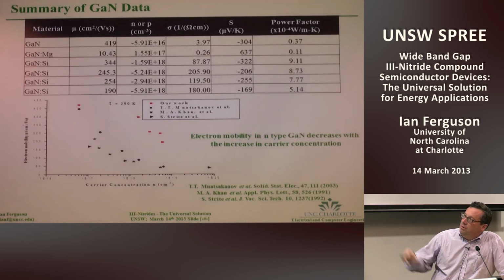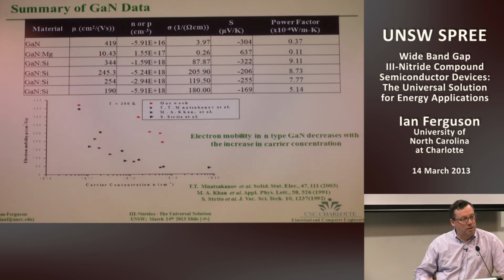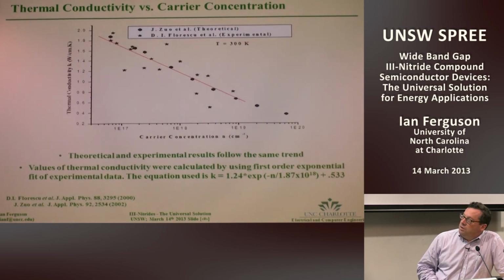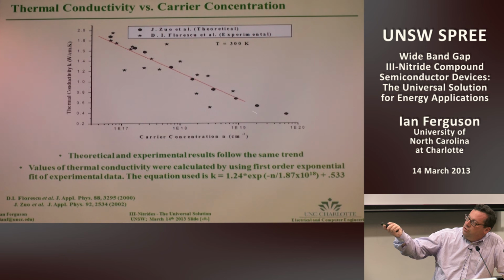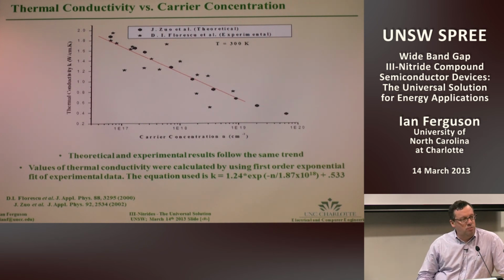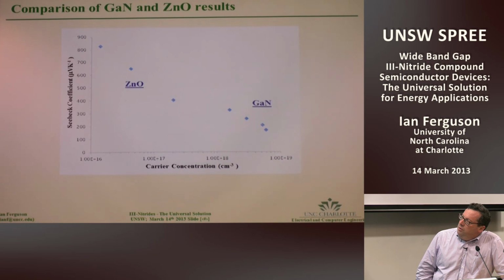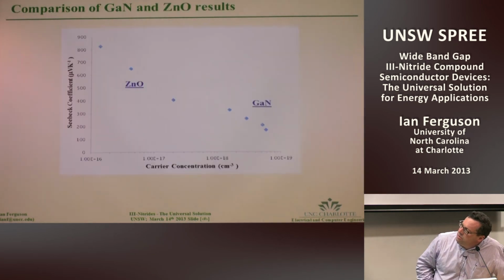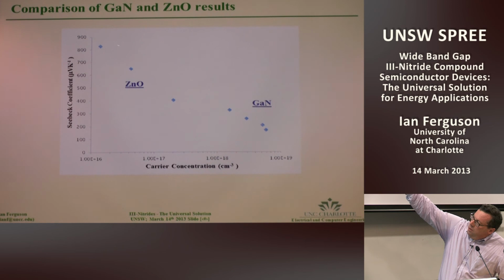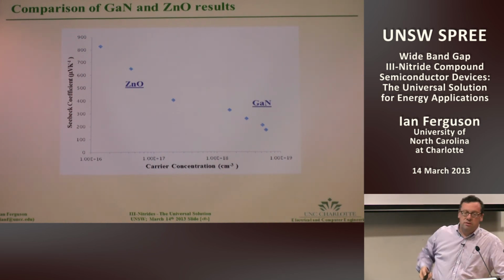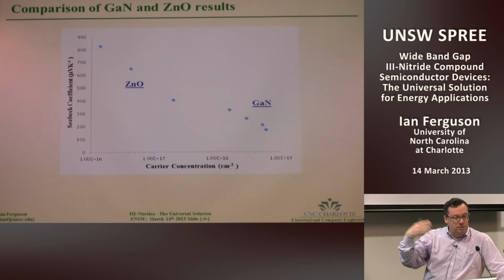So we started looking at gallium nitride, at scattering mechanisms and Seebeck coefficients with doping concentration within these layers. I'd done work before with this chap measuring thermal conductivity, and we set up to do the 3-omega method. We've also done some reflectance measurements with other people in the nitrides. We also did this for zinc oxide, and on this graph we've got other points down here. All this stuff is highly materials related, so it depends on the quality of the material.